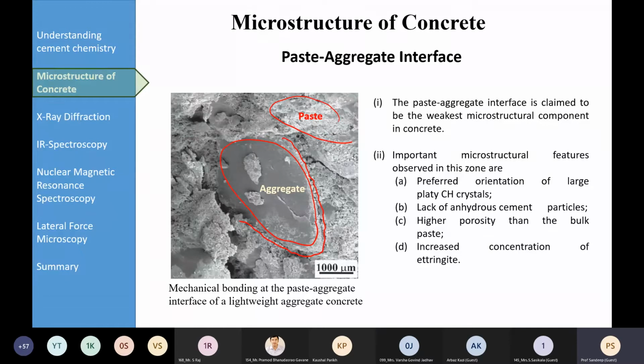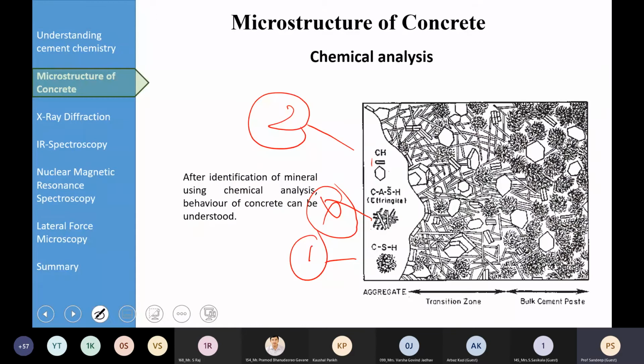There are certain important microstructural features observed in this zone. One, you'll see a preferred orientation of large platey CH crystals in this zone. There will be a lack of anhydrous cement particles in this zone, and this zone has a higher porosity as compared to the bulk paste available in the nearby vicinity. And there's an increased concentration of ettringite here. And how do we identify ettringite? Ettringite is a sort of needle-like structure, as we have seen earlier also. Like these needle type of structures, they are ettringite. You can see here, these needle type of structures are ettringite.